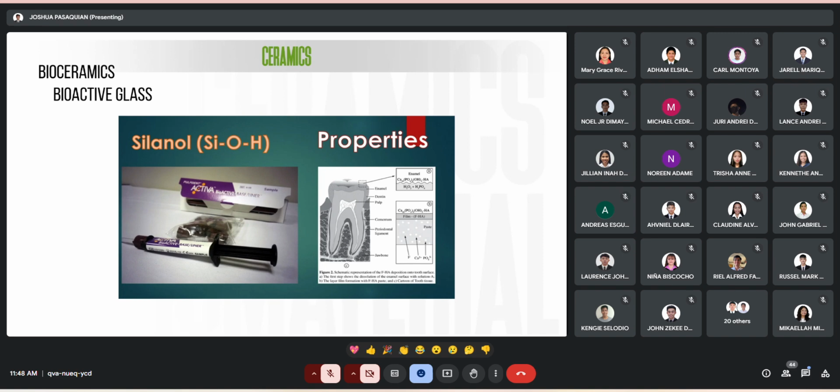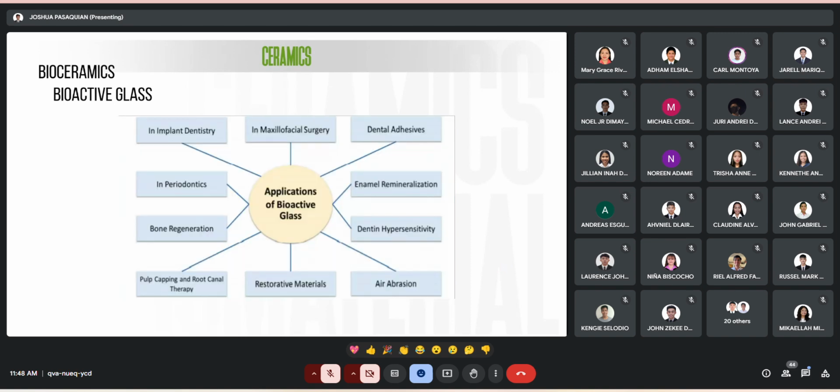Bioactive glass has a very important role in combating peri-implant disease since its bioactive properties prevent inflammation and infection of vital tissues. Bioactive glasses also have shown to possess broad spectrum antimicrobial properties with no observed resistance to date. Once embedded in the body, bioactive glasses increase the pH and osmolarity locally as part of their hydroxyapatite deposition reactions. This creates an environment unfriendly for bacterial growth.